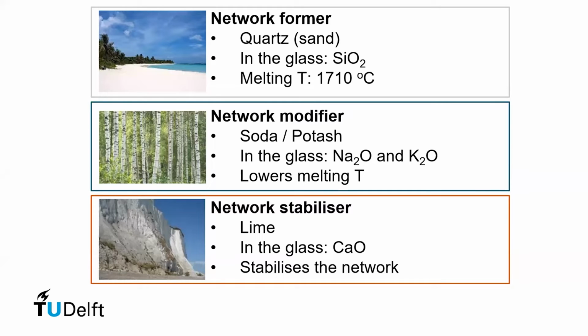But in order to work with this, to melt it, you would need to achieve a very high temperature, and the glass makers in the past weren't able to do that, so they started adding other ingredients to the network, like network modifiers in the form of soda or potash, which changes the glass structure and lowers the melting temperature so that they could actually make a glass melt. But that changes the glass network, and it makes it less chemically stable.